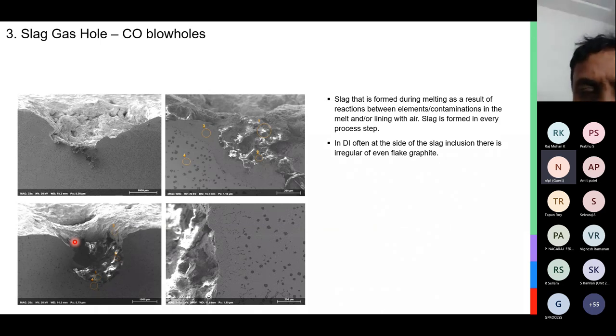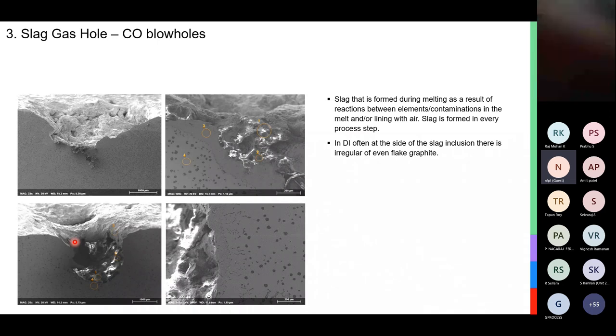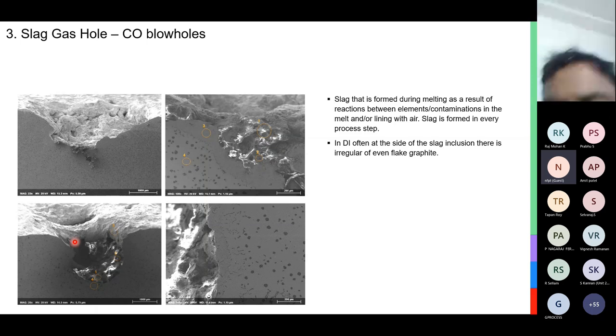Slag, it's a completely different ballgame when it comes to ductile iron. In ductile iron, slag has a much greater tendency of formation because of the most differentiating factor, magnesium, and the ferrosilicon magnesium treatment. There can be slag caused during melting that comes into the system through the treatment ladle, and there can be slag generated during the metal treatment because you have so much reaction violence, so much turbulence, and so much interaction with atmospheric oxygen. So there is a strong tendency of slag coming into the system.